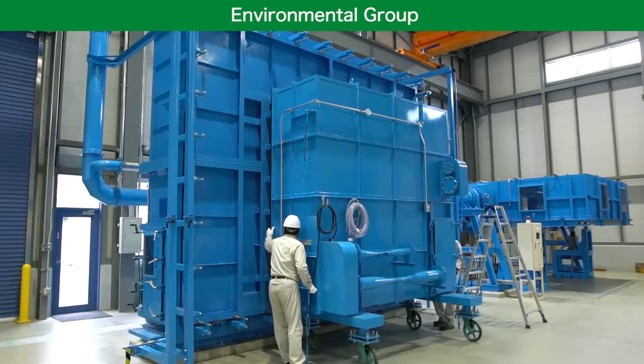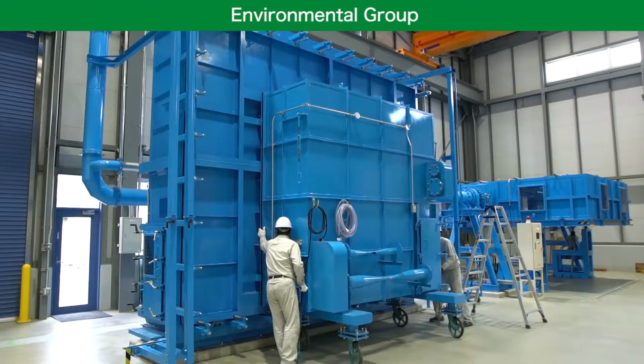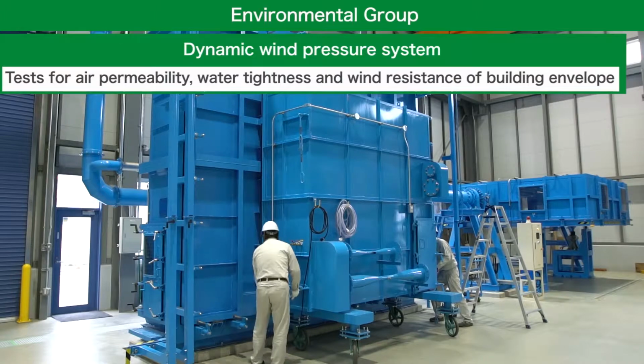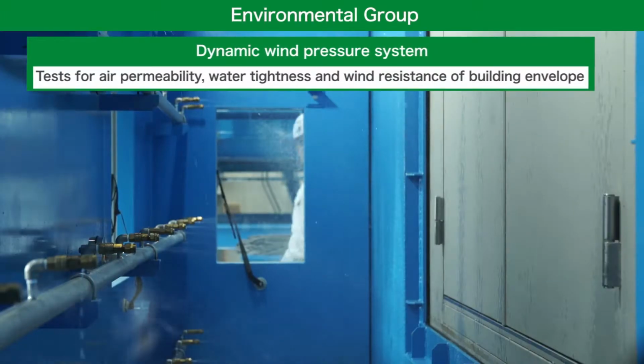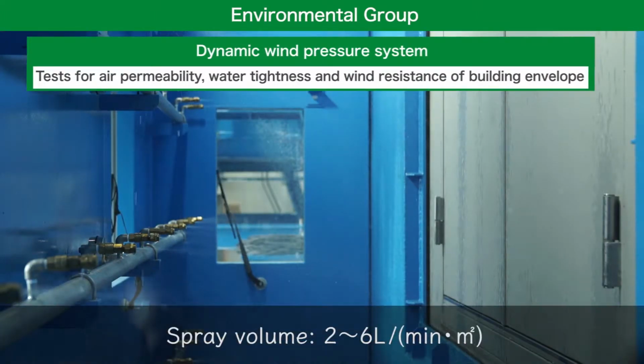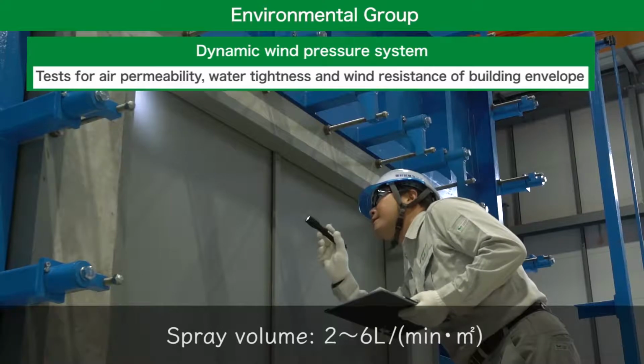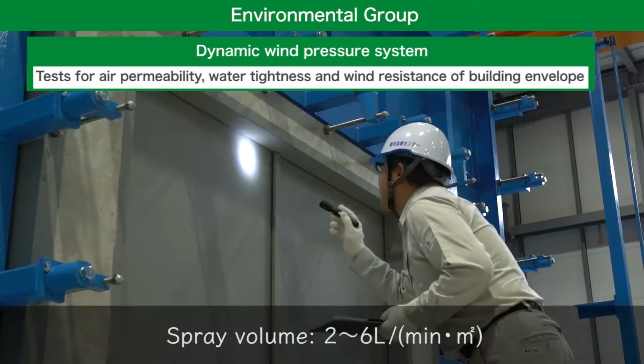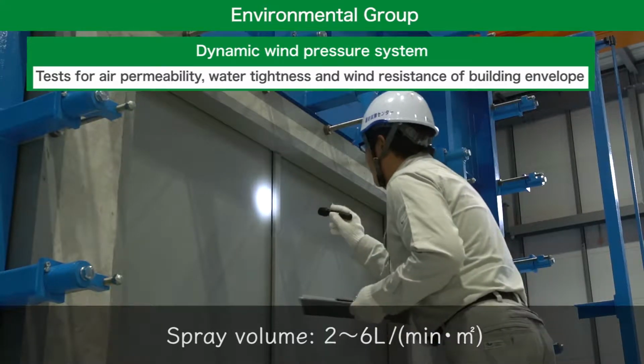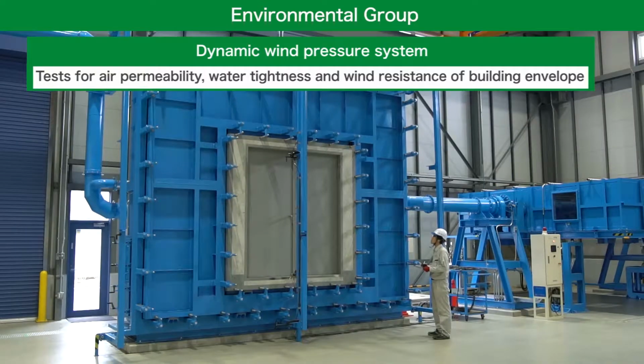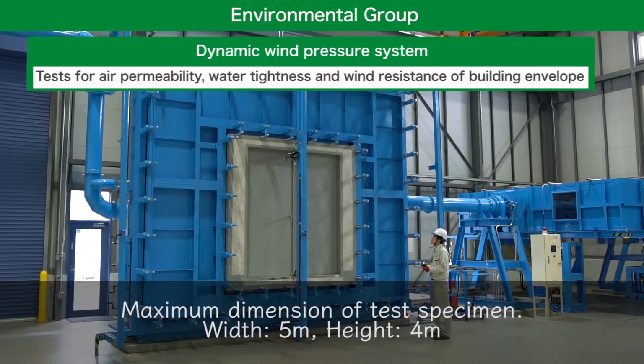The dynamic wind pressure system is used for tests for air permeability, water tightness, and wind resistance of building envelopes such as roofs, walls, windows, and door sets. A test piece of a maximum of 4 meters in height and 5 meters in width can be tested. A maximum of 10,000 pascals of load pressure will be applied, and the spray volume will be 2 to 6 liters per square meter per minute.